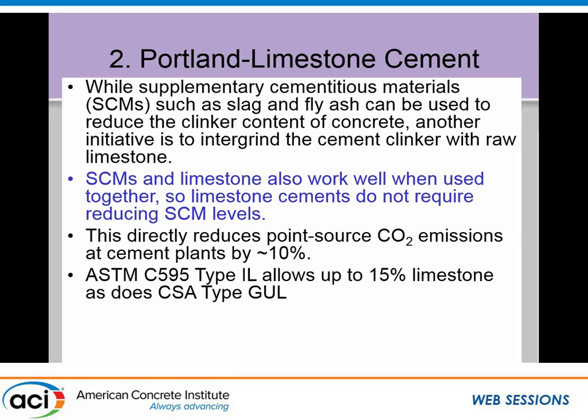Now we can reduce the amount of cement in the paste. And that's where the limestone comes in. I mean, it's old news now. ASTM C595 has this Type IL cement. It's been around, I'm thinking, 5-6 years now. It's been around for 10 years in Canada, equivalent type, call it a GUL. And as I said, these things work well together because they form carboaluminates. The carbonates from the calcium carbonate, interground carbonate, react with the aluminates in the cement. They also react really well with the aluminates in fly ash or slag to form more carboaluminates, and you actually get enhanced one-day strength at the same SCM replacement with the limestone cement.